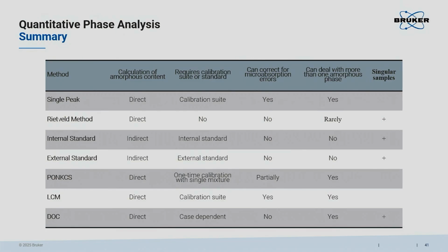There are some requirements which may be important. Single peak quantitative phase analysis usually requires a calibration suite. You can also do I over I corundum, as we learned yesterday. But I over I corundum, the way we've seen it, is a truly semi-quantitative method. With the calibration function, you will get extremely accurate results. If you look at some work where people are quantifying polymorphs in pharmaceutical compounds, and if they do appropriate calibration suites, they get better than 0.1% absolute. So this is impressive. It can be done, but it cannot be generalized.